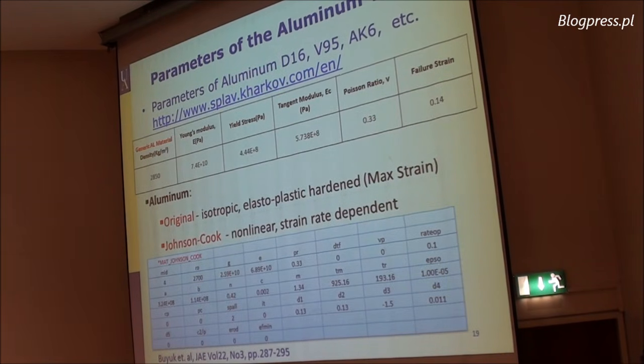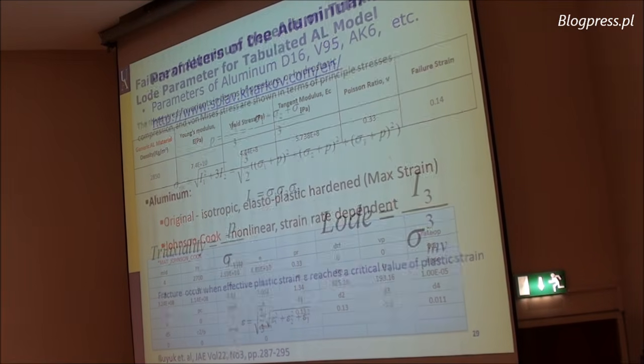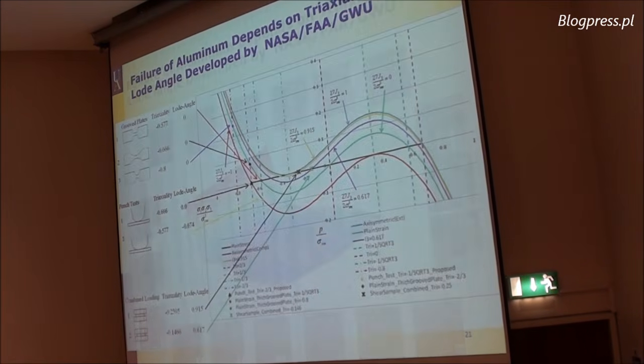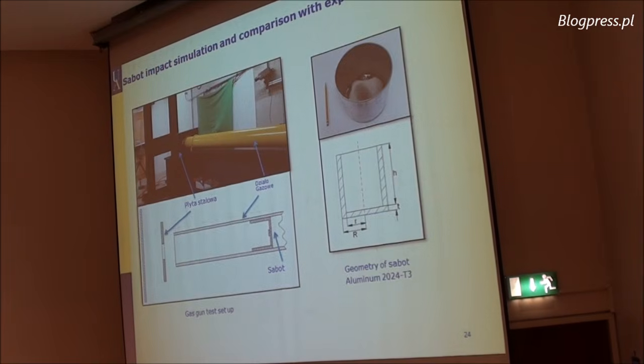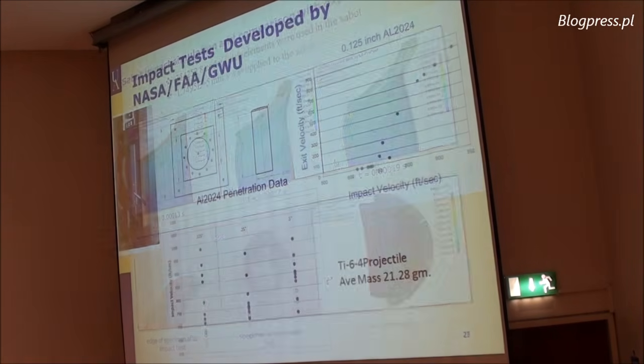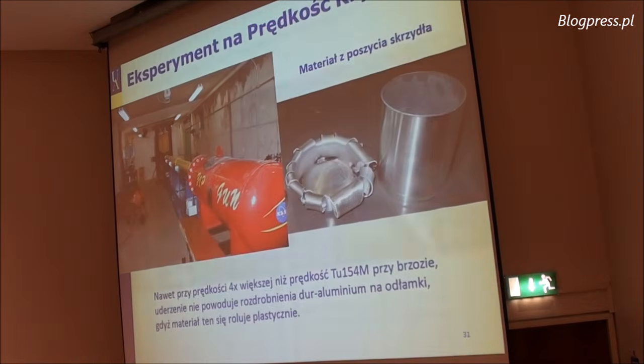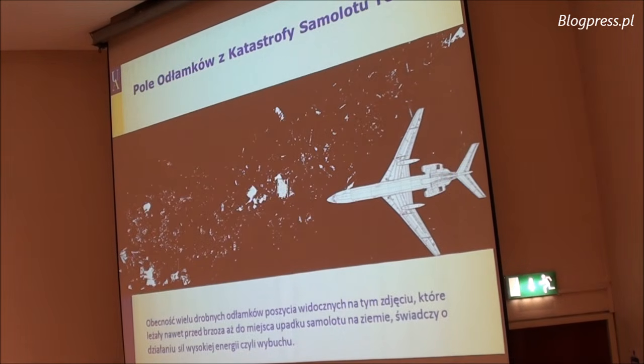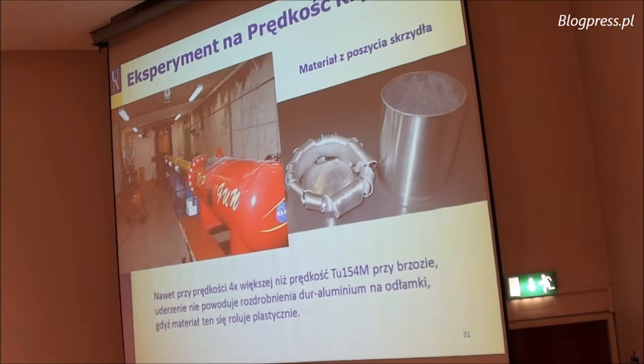Now for the aluminum, we used first a bilinear material model. We used Johnson-Cook, which is a strain rate dependent model, and recently we use this tabulated model, which is the most accurate that I already showed before here. Now, what is interesting is that this test that I mentioned proves that this material is very plastic.